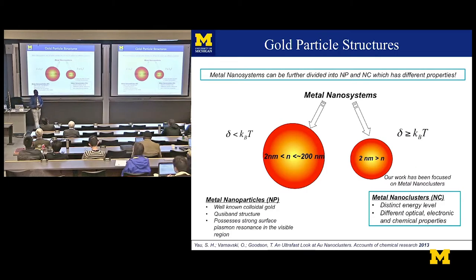People were making small clusters in the gas phase in about the 1980s, the late 80s. They could make these clusters by different methods under high vacuum, like gold 5 minus and so on. They found that if you make particles of this dimension, you can still describe them as nanoparticle behavior. But if you made particles smaller than this, it wasn't clear how to describe them. The Mie scattering approach seemed to fail. And so this left a really interesting question.